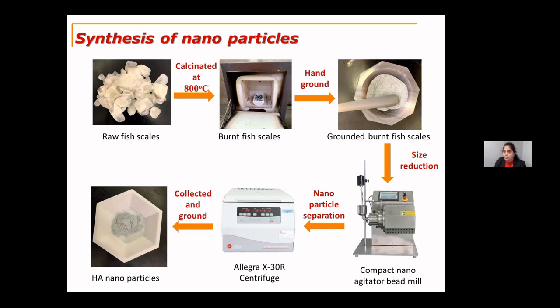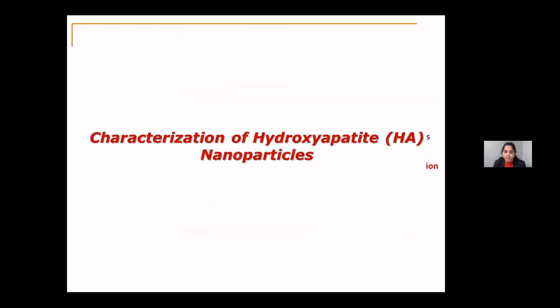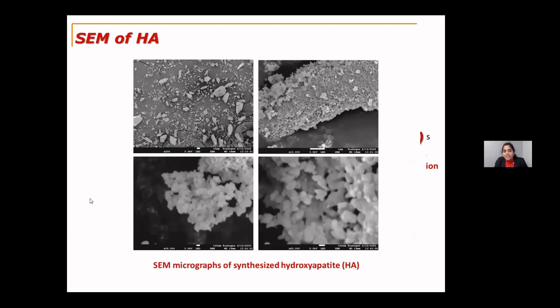And in order to confirm this size, we further characterize these nanohydroxyapatite particles. So here we discuss the characterization of the hydroxyapatite nanoparticles. These are the scanning electron micrographs of the synthesized hydroxyapatite. This is at a magnification factor of 300, and this is at a magnification factor of 15,000. Hydroxyapatite particles easily agglomerate, so we can see the agglomeration here, and also a kind of porous structure. And this is 35,000 magnification, and this is 60,000 magnification. We can see that the scale is 100 nanometers, so this size is definitely at the nanoscale.